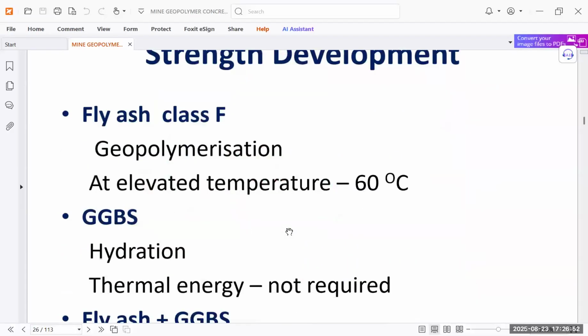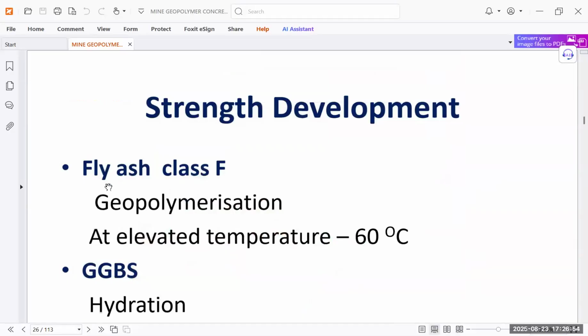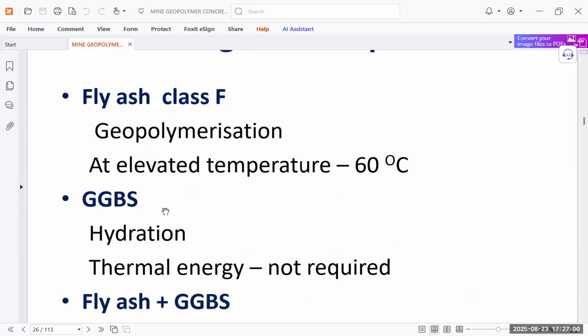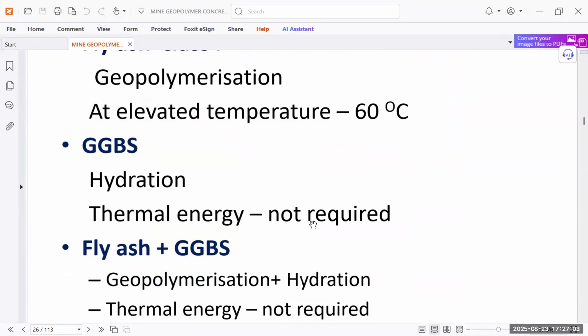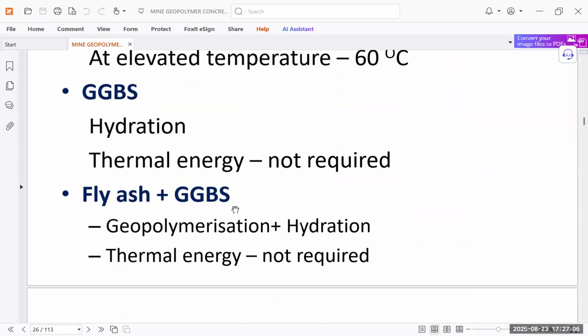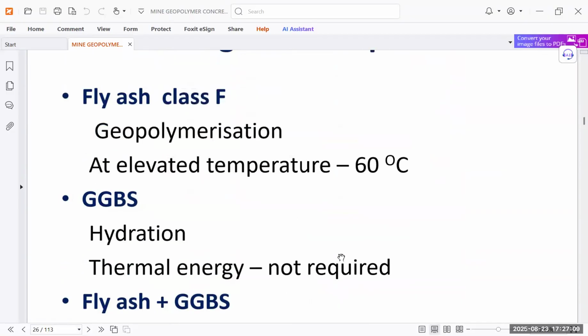So as we know, there are different kinds of fly ash. When fly ash class F is used, geopolymerization occurs at an elevated temperature of 60 degrees Celsius. And when GGBS is used, hydration occurs and thermal energy is not required in this case. And if we use fly ash plus GGBS, then geopolymerization plus hydration occurs, and thermal energy is also not required.